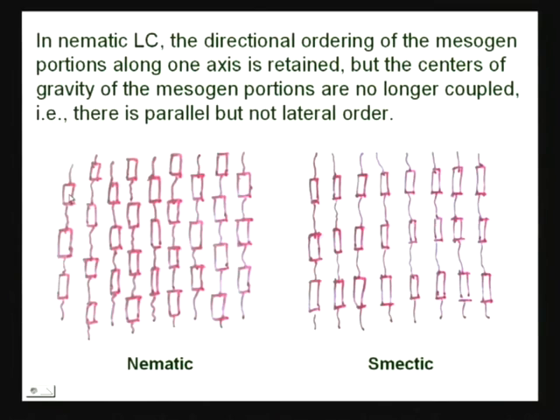So, now the distance between this mesogen and this mesogen is quite bigger than this one. So, this mesogen is close to non-mesogenic portion. That is why the interactive force which contributes to the viscosity in the liquid phase, here it is supposed to be less. In fact, it is the case in reality we find that nematic materials, nematic LCPs are of low viscosity. We compare this one where these molecules are aligned parallel, here also these molecules are aligned parallel, but not the mesogens are aligned parallel.